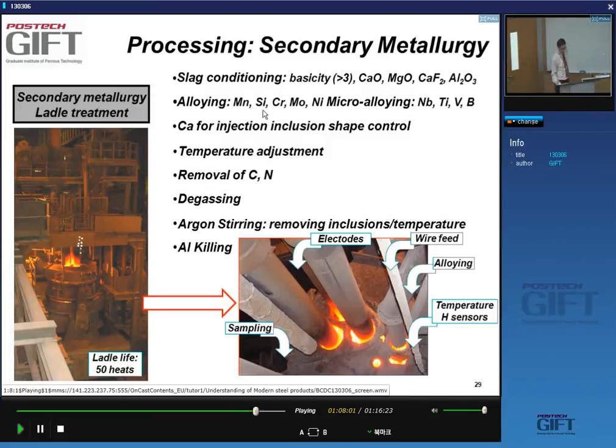Of course, you need to adjust the temperature. The reason is because you will need to cast your metal, and you want to be casting at the right temperature. You can still, if needed, continue removing carbon and nitrogen. Usually that's done by degassing. You also do a lot of stirring in the ladle. You do stirring to allow removal of the inclusions by increasing the contact time between the metal and the slag. And finally, you also do aluminum killing.